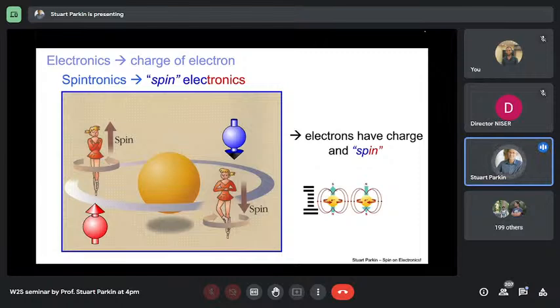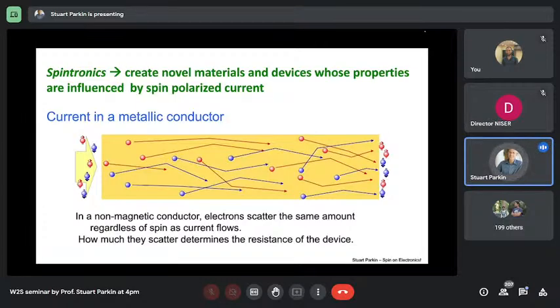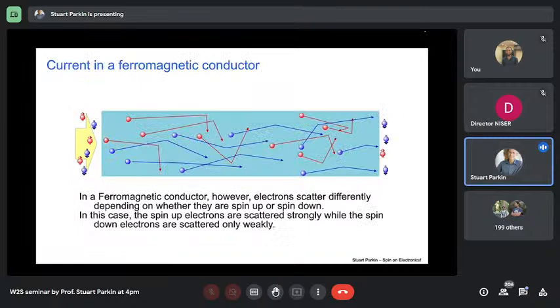And then it turns out we can create spin currents in a very simple way. First of all, if we take something like copper, copper has equal numbers of spin up and spin down electrons, and when current flows through this material, the current is carried equally by these two types of spin polarized electrons. But it was known in the 1930s that if you pass current from, let's say, a battery where it's unpolarized into a magnetic metal whose magnetization points in a given direction, then the current quickly becomes carried predominantly by one type of spin polarized electron.